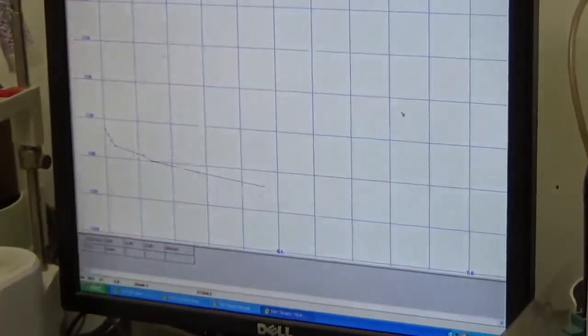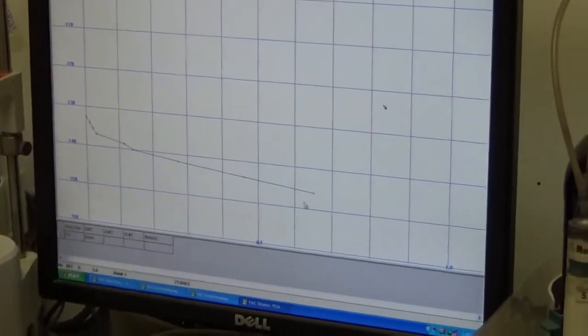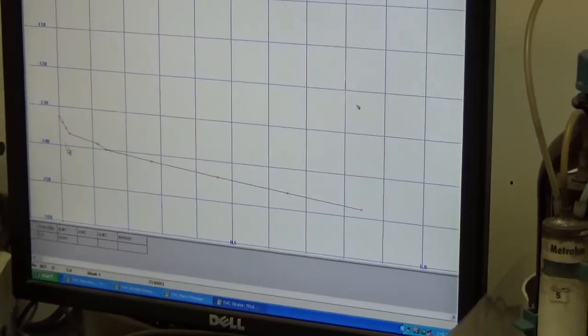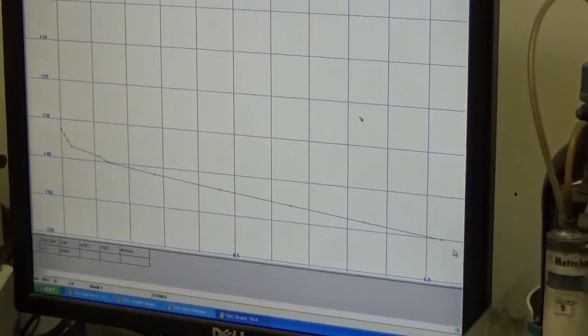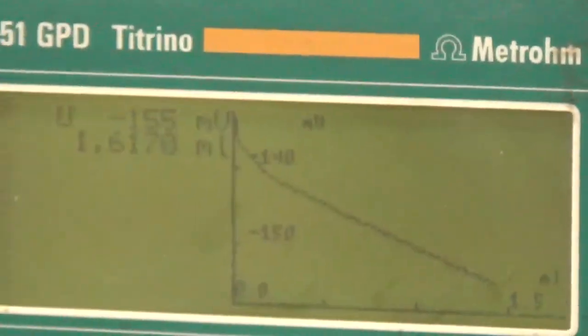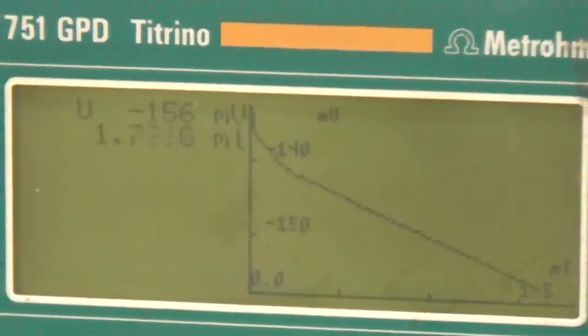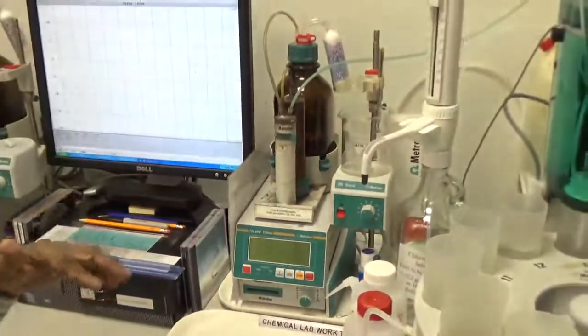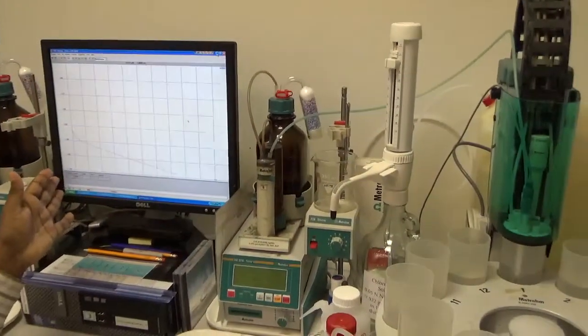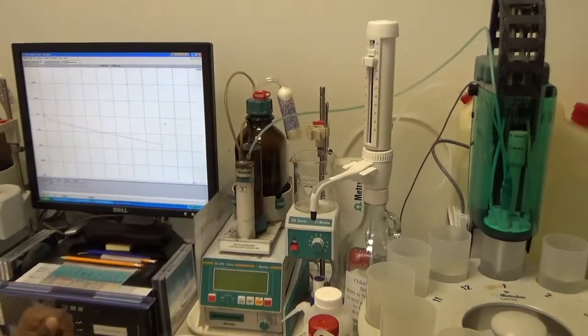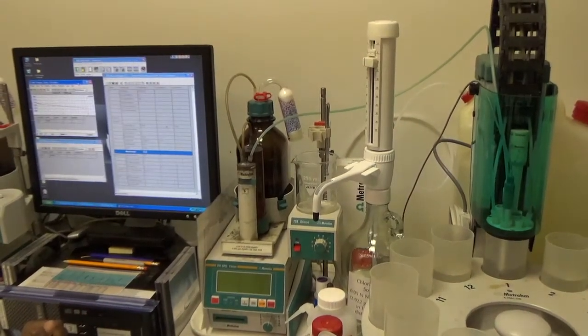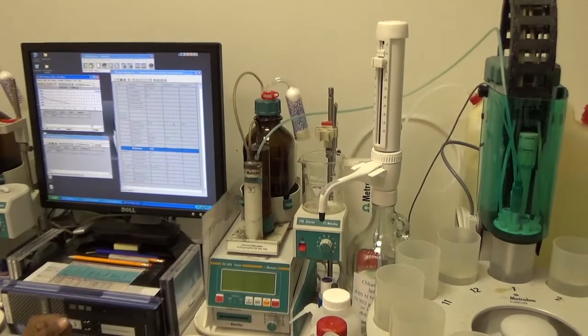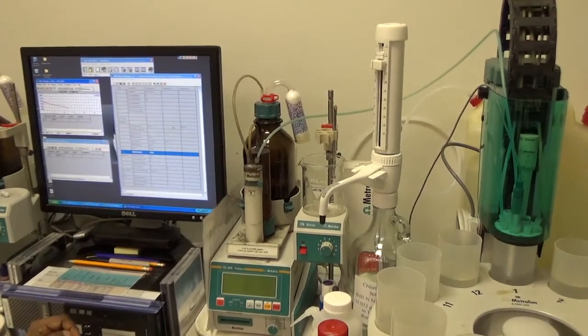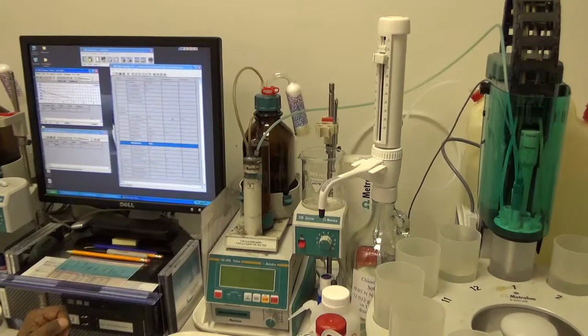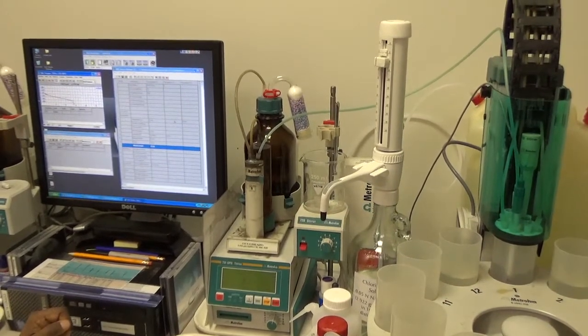Every increment of silver nitrate added is shown here along the x-axis, and the millivolt change along the y-axis. Since I added around 5 milliliter of sodium chloride, the equivalence point will come somewhere around 5. It also depends on the amount of water added in the solution. Here we see the plot.